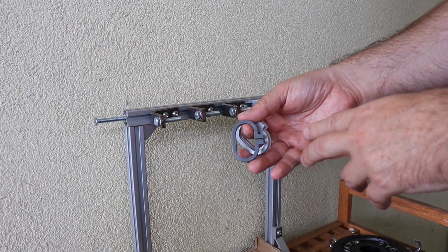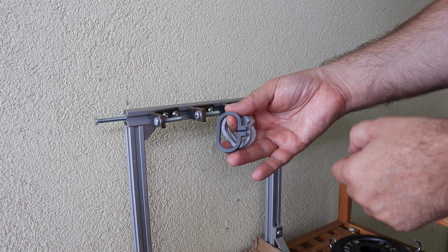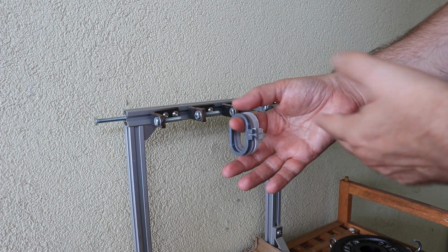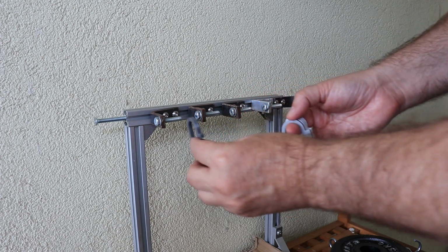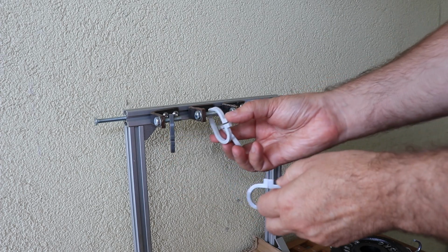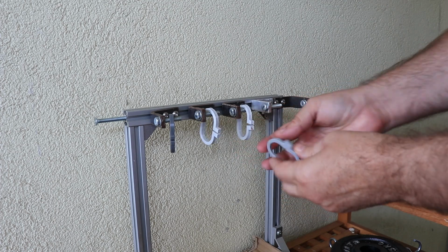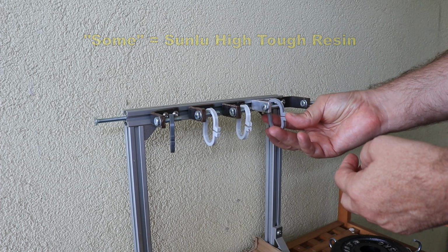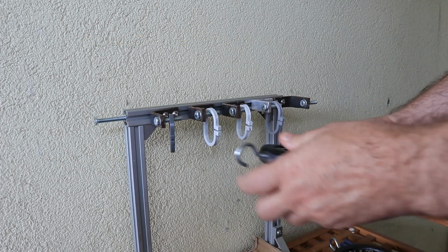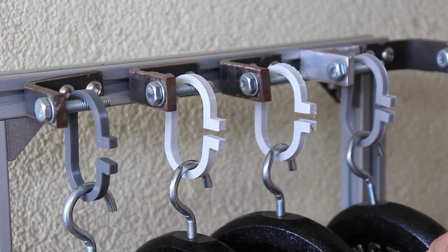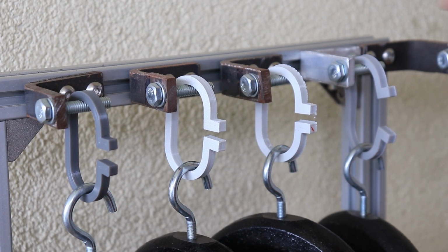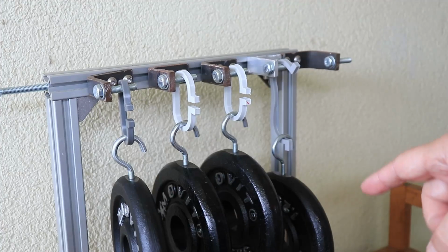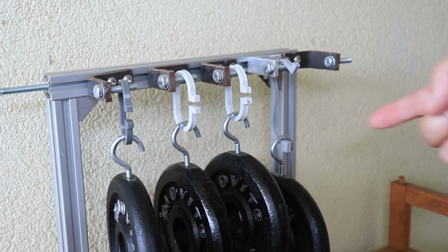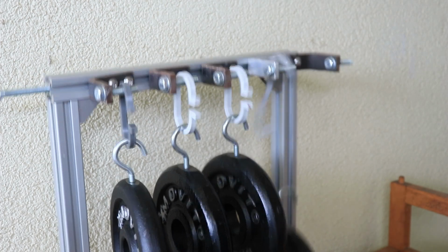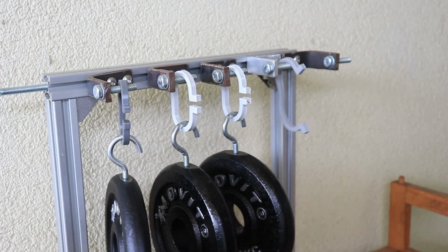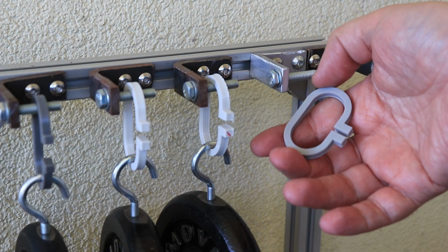And now my regular creep test, where I am measuring the deformation distance between 2 reference surfaces under a constant load. And I have 3 experiments in progress. At least we have some comparison between them. So this one is the easy ABS, this is the PLA, this one is the annealed PLA, and this is some resin material. The load will be 1.25 kilograms as always. And I can see the resin will not survive even the first 10 minutes. What a moment. And what is interesting, the next day it got back its original shape.